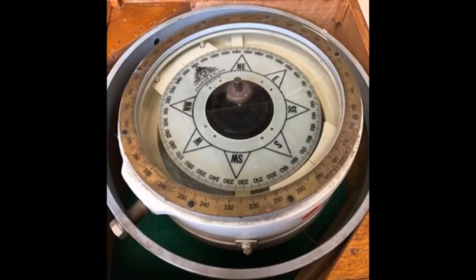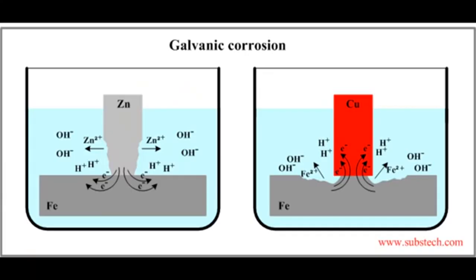But, of course, if it sounds too good to be true, it usually is. And in this case, there were a number of issues that were less appreciated at first, and at least until after the first generation of iron warships had been laid down. The mass of the iron in the ship's hull affected the magnetic compasses that were used for navigation. The copper plating that was used to keep marine growth away from ships' hulls induced a galvanic battery reaction with the iron of the hull when the ship was immersed in salt water, and this corroded both of them to nothing in fairly short order. And having your ship literally dissolve itself away into nothing is a pretty good party trick, but not really good for the long-term health of the crew.